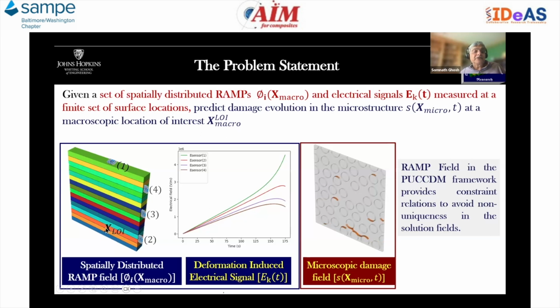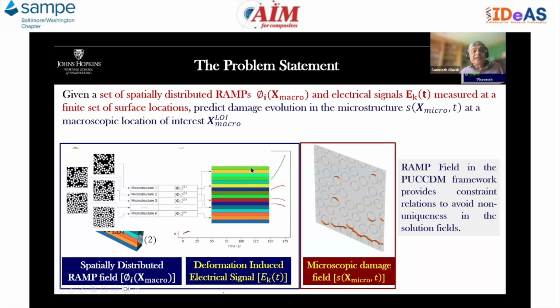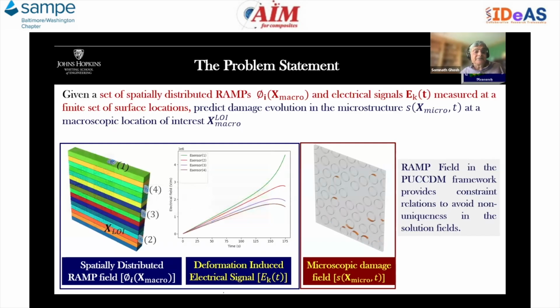So at any given location of interest, can I predict just from these few surface-based sensors? These are the measurements of the electrical field as a function of time at the different sensors. Correspondingly, these are layers that are represented by different ramps corresponding to different microstructures that you're seeing here. The ramp field in the PUCCDM framework provides a constraint relation to avoid non-uniqueness. If you don't have enough of these ramp gradients, then you need a lot more of these surface-based sensors in order to provide uniqueness in the predictions.